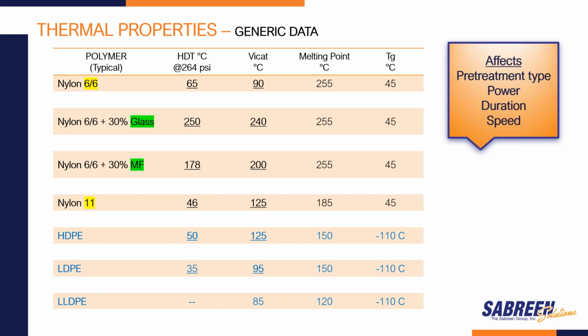If we take an extreme case of nylon, and your design engineer initially says, well, the material we're going to use is nylon 6/6 plus 30% glass. That's the second row that I'm showing. Well, it has a heat deflection temperature at 264 psi of about 250 degrees centigrade, a Vicat softening point of 240 degrees. Let me back up just a moment and tell you that the thermal properties I've stated on this slide are very generic data.